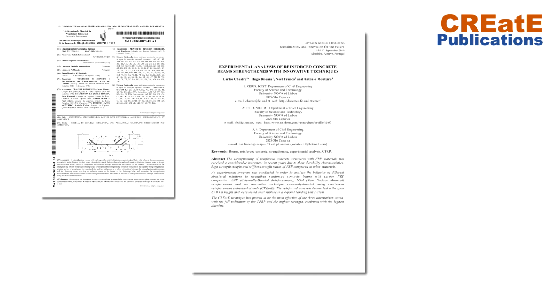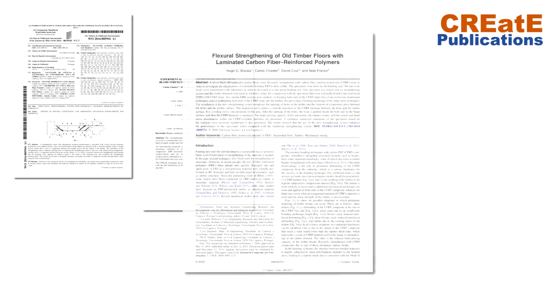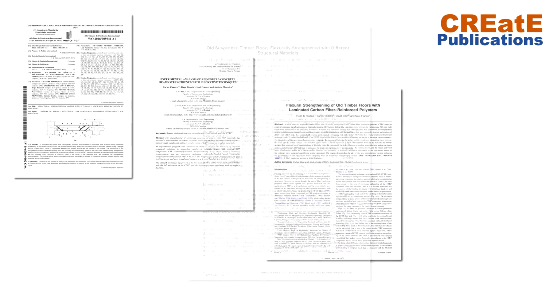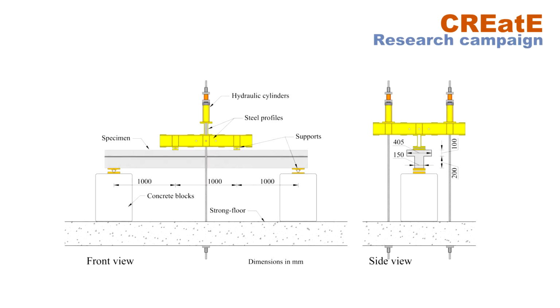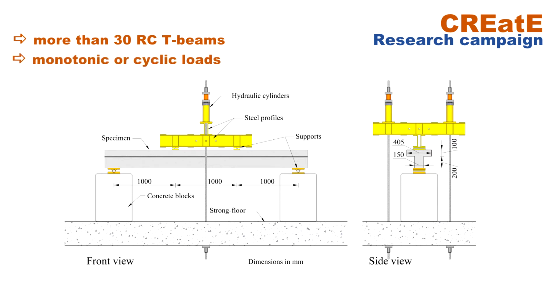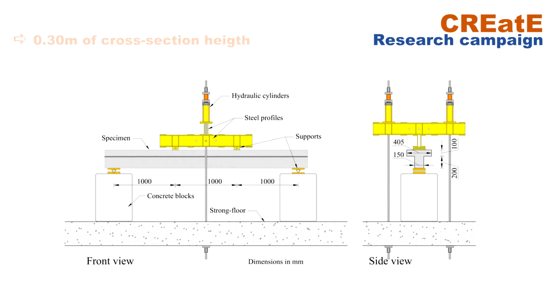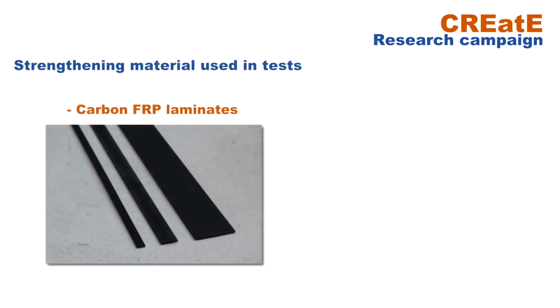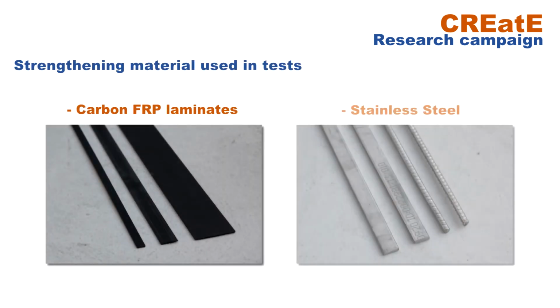Meanwhile, some scientific papers have been published in international journals with the test results proving the validation of the CREatE system. This video shows the research campaign results involving more than 30 beams. The tests were performed at natural scale in reinforced concrete beams under monotonic or cyclic loads. The reinforced concrete T-beams had a cross-section height of 30 cm and a free span of 3 meters. The CREatE system was tested with carbon FRP laminates and stainless steel bars.